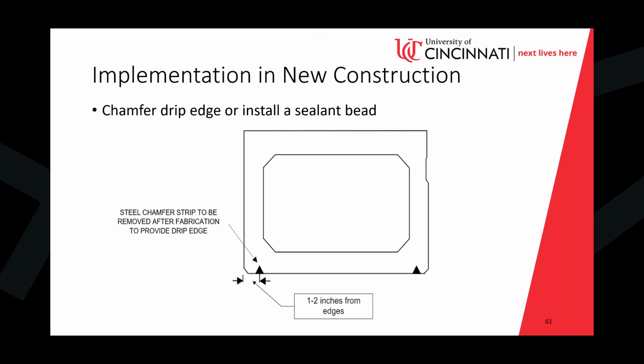And then if there's concerns about creating this strip that is a removal of material in that area, another option that would involve not having to insert a strip that you would remove, but to just apply a sealant bead. So apply a sealant material where this strip is currently being shown as applied to the surface, and that would do the job of acting as a drip edge to get that water off. And it's not then cutting into the concrete.